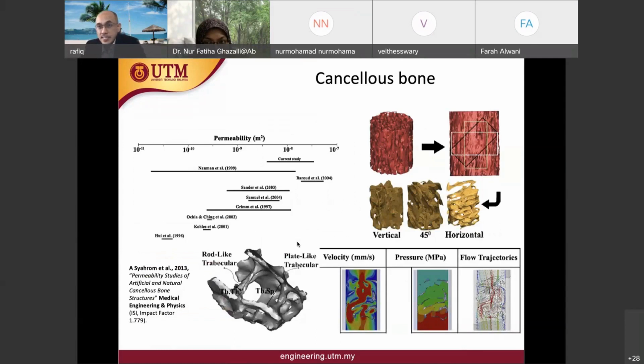We also utilize the finite element model that we obtained from this micro CT scan to analyze permeability. The reason we want to analyze permeability is that we want to develop our own simplified cancellous bone, if you like. Because cancellous bone is very unstructured, but of course we can measure the porosity and density. If we can study the permeability of this structure, then perhaps we can develop our own simplified version of cancellous bone. Later, I will show you some of the simplified versions that we developed.